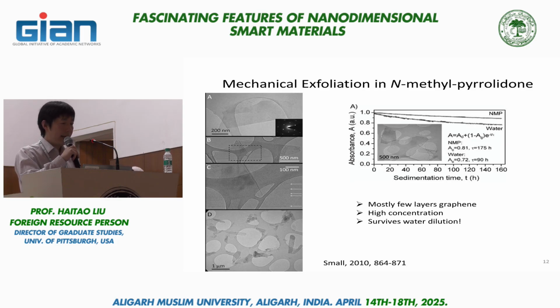So they can get a variety of graphene flakes. On the left-hand side are transmission electron microscopy images showing different graphene flakes. In the middle is UV absorption of the suspension. Basically it shows that the suspension is stable even after 160 hours. Only about 10% of these flakes are being precipitated out.